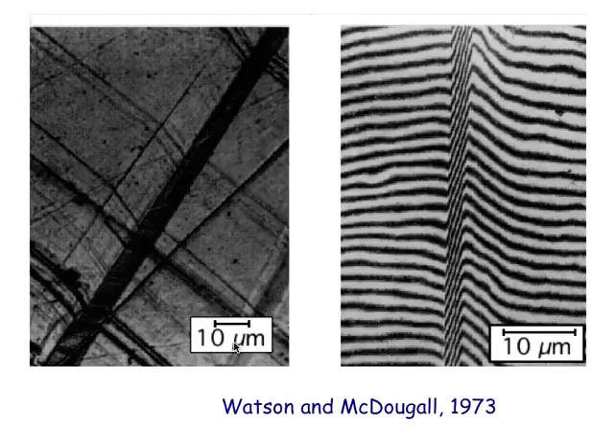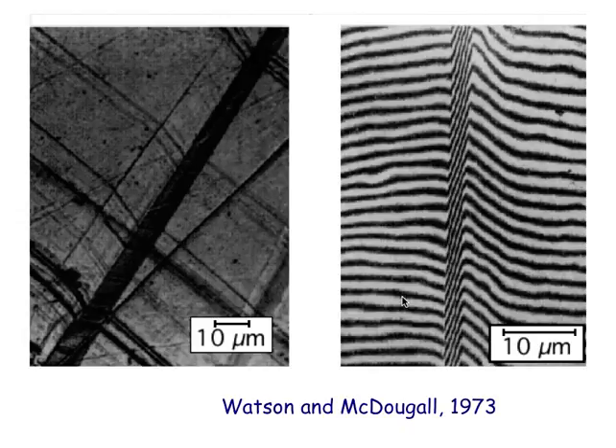Again, look at the scale here — this is quite coarse. Similarly, we can use interference fringes. If we have a half-mirror slightly inclined to the surface, you get interference between the reflected and the incident beam, and every so often it's out of phase, so you get a series of fringes which basically define the surface displacement. You can see this fringe is sheared and there is another shear on this side as well.